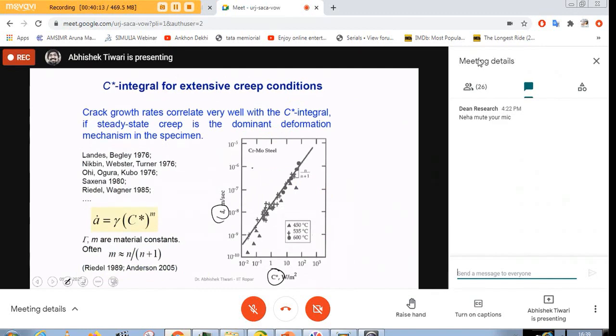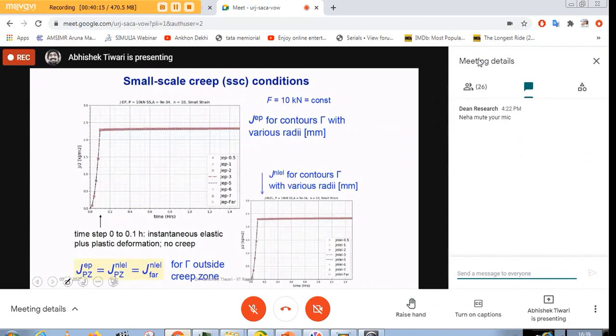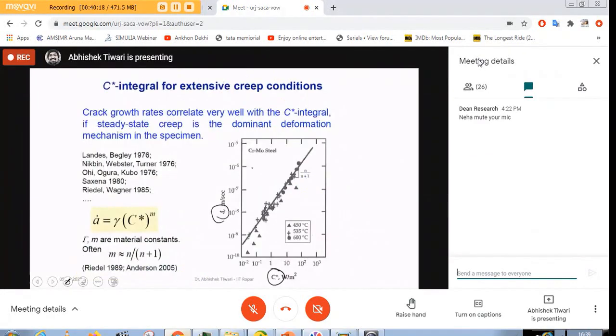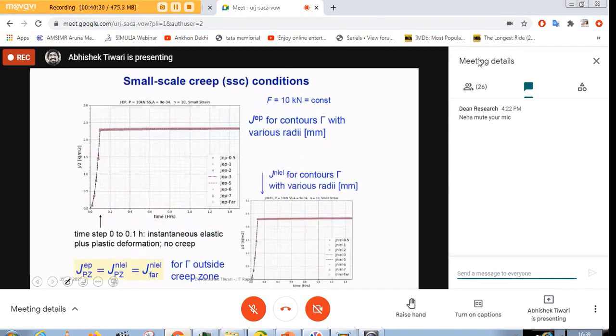So I did some calculation in creep deformation for small scale creep, and found that this integral C star is not path independent in a small scale creep. It only works in the extensive creep condition, meaning that the whole specimen is creeping. So I did the simulation in the small scale creep, meaning that, as in the earlier slides with the plastic zone, in this case we will have a creep zone, where this part of the material is deforming with a time dependence and the rest of the material is deforming elastically.